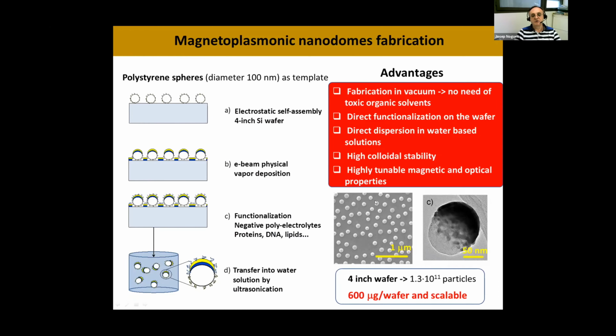I show you here a SEM picture of the self-assembly of the polystyrene spheres and a TEM picture of the final nanodomes. Actually, using this 4-inch wafer, we create about 10^11 particles per wafer, which translates into 600 micrograms per wafer, and is easily scalable to larger wafers.